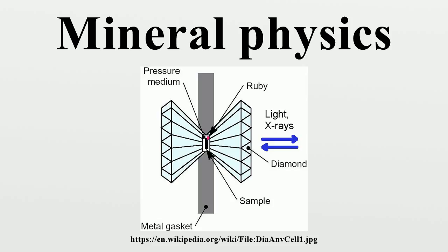Laser heating is done in a diamond anvil cell with Nd:YAG or CO2 lasers to achieve temperatures above 6,000 K. Spectroscopy is used to measure black body radiation from the sample to determine the temperature. Laser heating is continuing to extend the temperature range that can be reached in the diamond anvil cell but suffers two significant drawbacks. First, temperatures below 1,200 degrees Celsius are difficult to measure using this method. Second, large temperature gradients exist in the sample because only the portion of sample hit by the laser is heated.